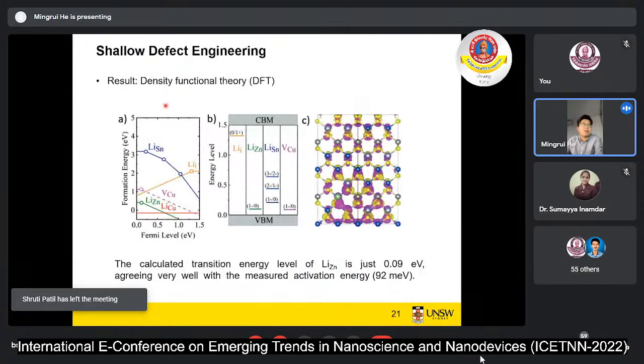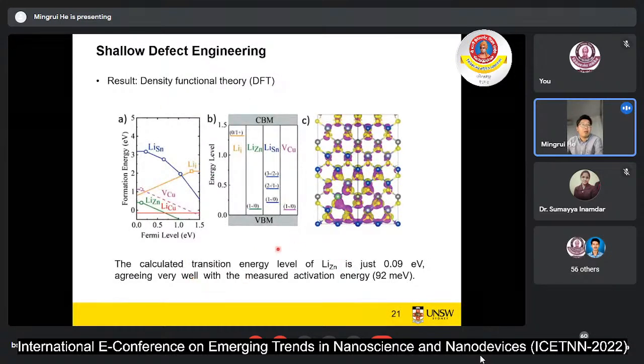So what we did is we did some DFT calculation. According to the DFT calculation, the lithium zinc anti-site defect is around 0.09, which quite agrees with the one we measured, 92 meV. So we can strongly conclude that the shallow defects in our materials have been changed.